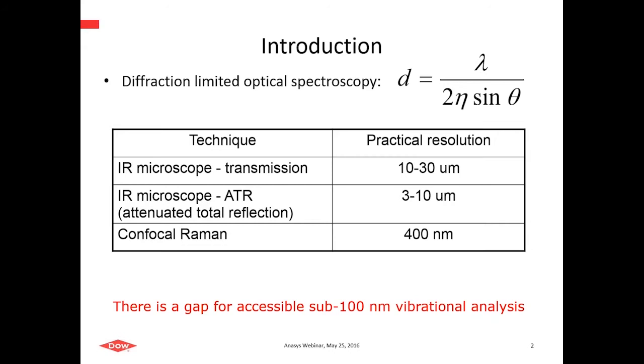In conventional IR transmission microscopy, in the mid-IR, that resolution would be about 10 to 30 microns laterally. ATR is a little bit better, primarily because we're using higher refractive index optics with the ATR crystal. That improves it maybe by a factor of 3. Confocal Raman microscopy gets us better resolution because we're using a shorter wavelength of light in the source radiation for scattering, and we have confocal optics in that path. But clearly nothing there gets us where we want to be in the nanoscale. That is, there's a significant gap for accessible sub-100 nanometer vibrational analysis.